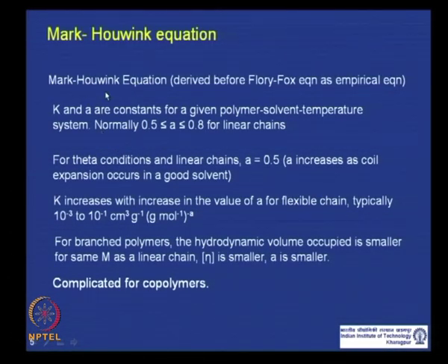So, as I said, the Mark-Houwink equation was derived before the Flory-Fox equation, as an empirical equation. Now, K and a are constants, as we just discussed while deriving this expression, for a given polymer-solvent-temperature system. If you change any of these three, polymer, solvent or temperature, then the K and a values will change. This is only constant if you have the same polymer, solvent and temperature, because if you change any of them,